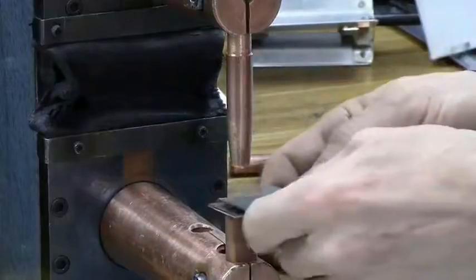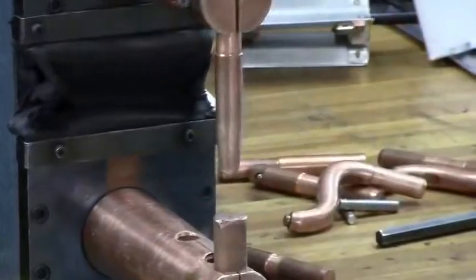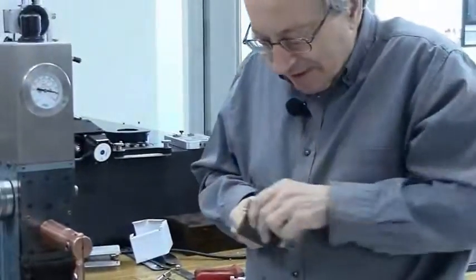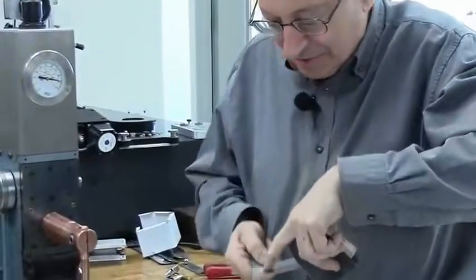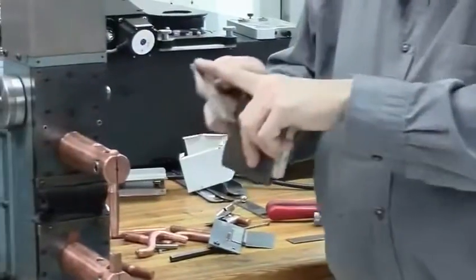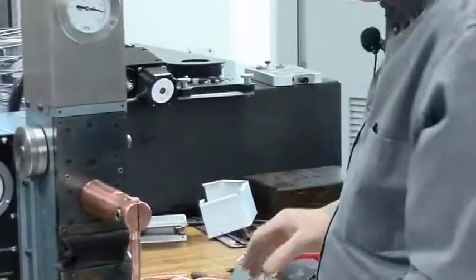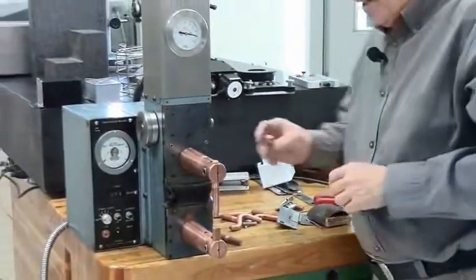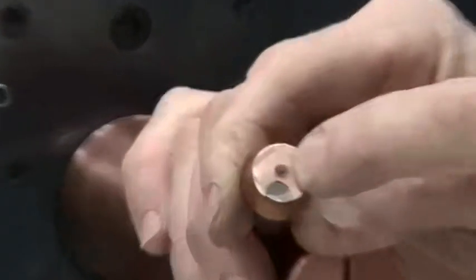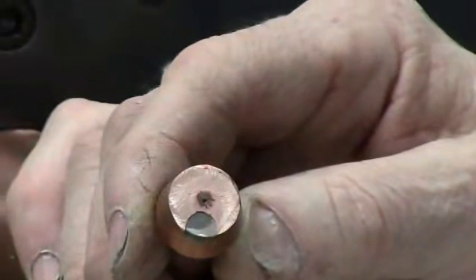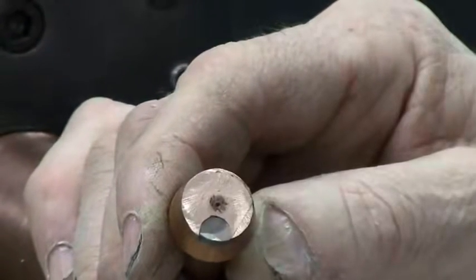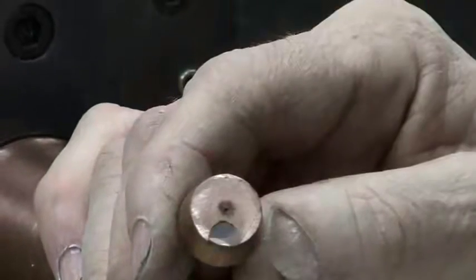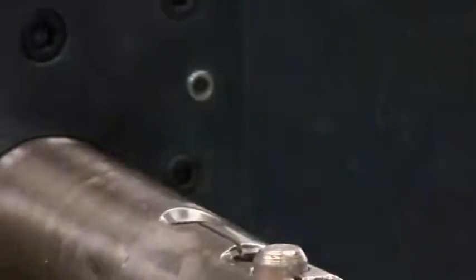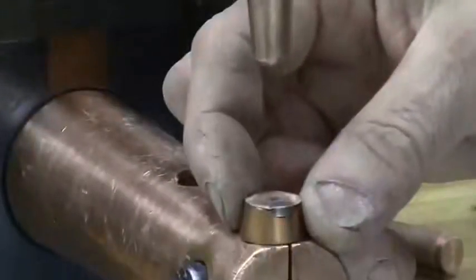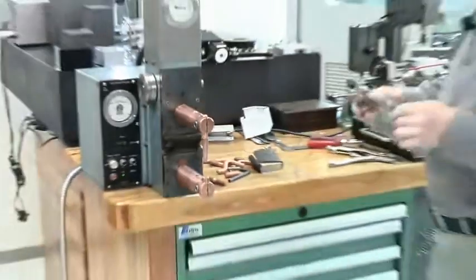Because although this is a completely flat electrode, the molten metal, when it solidifies, pulls in a bit, and when you try to sand it, there is still a mark, although in this case the mark was quite small, but it's in. Because it goes inwards, you have to sand the whole surface to get it off. So the way to get an invisible weld is to make a special electrode which actually has a very small dimple at the weld point. The dimple is maybe a few millimeters in diameter and maybe 50 micron deep. What it does is push the metal out into the dimple just by the amount which shrinks back when it cools down. So you end up with a perfectly flat surface. Okay, you still have to sand it a little bit, but at the worst you'll only have to sand off the bump, which is much less sanding than sanding the whole surface. Okay, so that's how to make invisible welds.